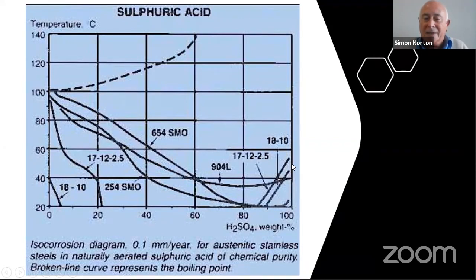If you look at those two diagonal lines, the top line is 316, 17% chromium, 12% nickel, 2.5% molybdenum. The 316 line, and the bottom line here, 1810, will be the 304 stainless steel. So if this sulfuric acid remained pure and he was at 98%, then he could actually operate up to about 40 degrees centigrade with his 98% sulfuric acid and only show 0.1 millimeter per year uniform corrosion in his piping.